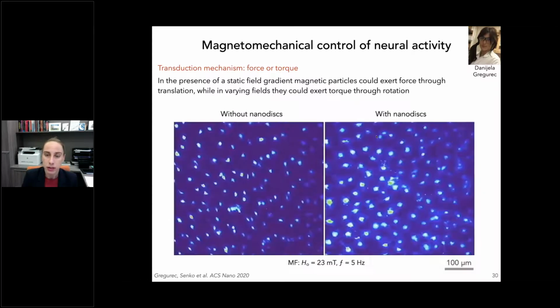And then when we expose these sensory neural cultures coated with magnetic nanodisks to very weak, very slow magnetic fields, you can see that they begin to light up. That means they're pumping calcium into them. That means they're getting excited.